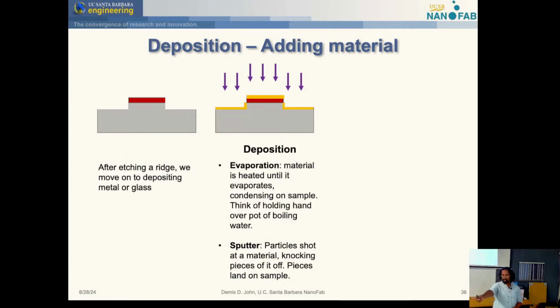It would be dark and black, and the filament had popped. And the reason is because you're literally evaporating the filaments. The bulb is a little vacuum chamber, and that filament is getting hot, and the metal is shooting off and coating the inside of the glass. That's why your bulb would turn dark gray, and the film is getting thinner and thinner until it pops. That's actually the same technique. We're just doing it in a large machine, basically.